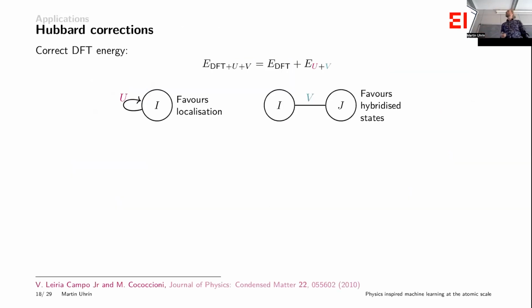So to give you a little bit more impression of what's going on, if you imagine we have some expression for our energy that comes from these calculations. We now want to correct that energy to try and fix some of this problem that the approximation caused in the first place. And there's two numbers. These are just scalar numbers that come into play in this, called the U and the V. So if you ever work in this field, you'll always see people talking about the Hubbard U or the Hubbard V parameter. Loosely speaking, what these are doing is the U parameter, the higher you make it, the more you will favor your electrons being localized onto your atom. So you will correct some of this problem, but you'll actually overcorrect it if you just do that. You need to introduce a V parameter, which acts between pairs of atoms to actually try and hybridize the states back a little bit. So you actually correct both parts of the problem.